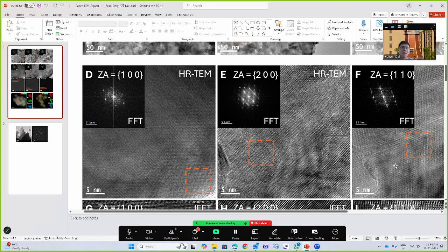So you can see that most of the areas are like a single crystalline with a spot, and they can be indexed actually. The result is slightly different from the single crystal XRD and synchrotron data. I analyzed all three FFT patterns, and none of them fits either the rhombohedral phase or the cubic phase fully. I was thinking it's locally probably something in between, and what you see from the diffraction is more like an average of everything. That's my assumption. For this phase, I'm not able to resolve what they are because it's too small, and